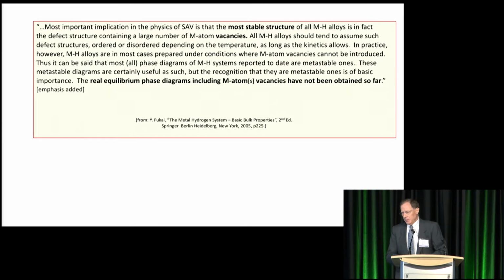This I am not able to skip. In fact, I have to read it to you line by line because I think it's very important. This is a quote from Fukai's book, which says that the most important implication of the physics of superabundant vacancies is that they're the most stable structure of all metal hydrogen alloys, and in fact, the defect structure containing a large number of metal atom vacancies. All metal hydrogen alloys should tend to assume such a defect structure, ordered or disordered depending on the temperature, as long as the kinetics allow.